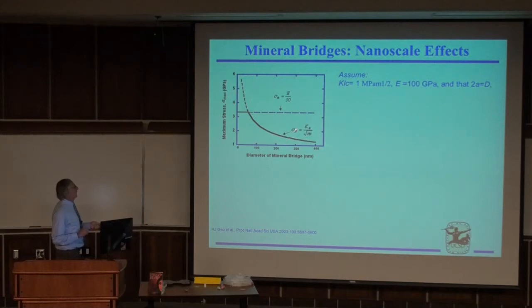We all know this equation for fracture toughness, K1C. It expresses the fracture stress as K1C divided by the square root of pi A, where A is the flaw. If you take the dimension of the bridge as equal to A, or 2A, as the bridge becomes smaller and smaller, the maximum strength would rise according to here. But this is the theoretical tensile strength of calcium carbonate, E over 10, approximately here. So these two curves will intersect at about 56 nanometers.